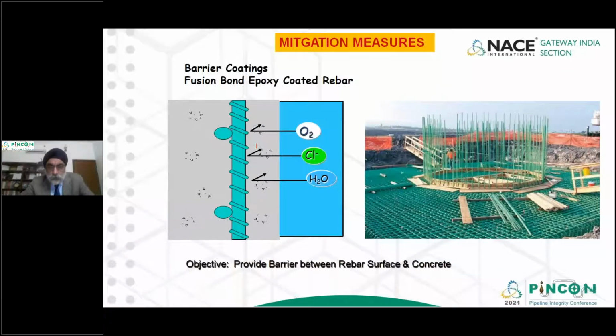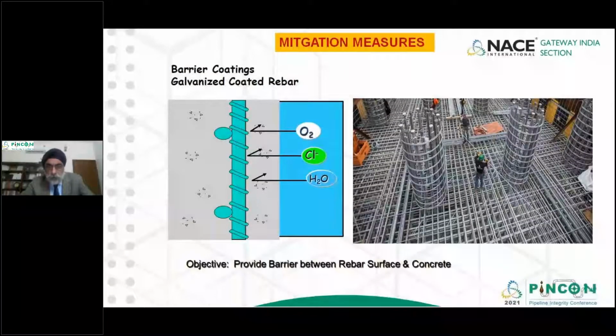This is a good strategy, but the main point to be noted is that during construction, the bending of the rebars has to be done properly, because if the FBE cracks when you are bending the rebar, then at the crack points, steel gets exposed to the environment and can lead to accelerated corrosion. The other strategy is to use galvanized coated rebar. This is normally used for above ground structures. Again, not being used too much in India, but commonly used outside India in many countries. There's a cost attached to it, but a galvanized coated rebar will provide the desired life to the structures.